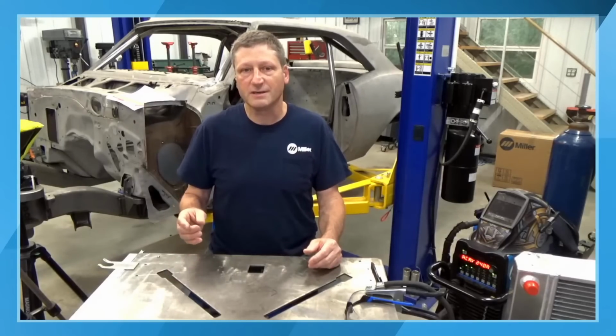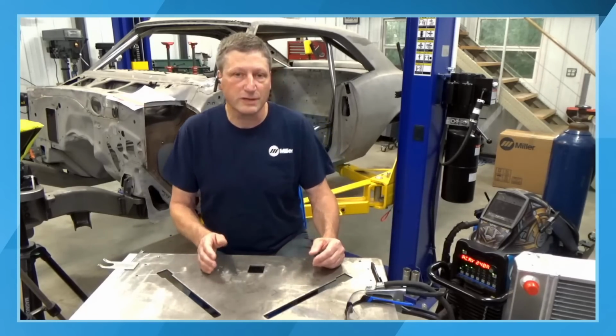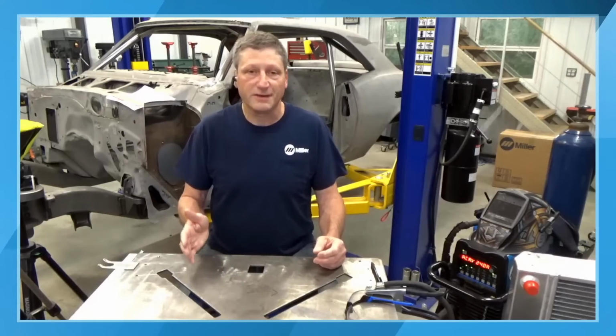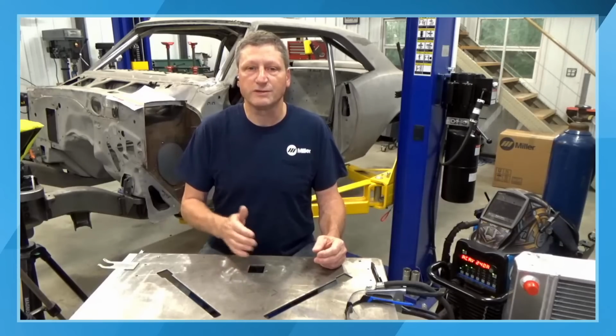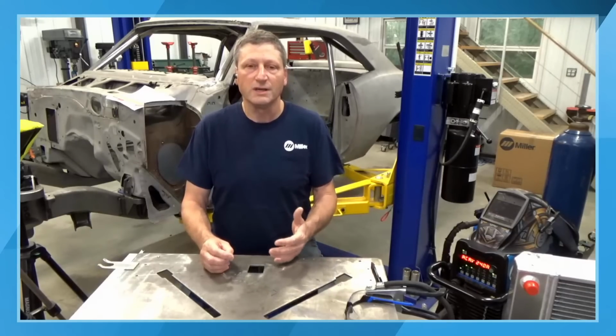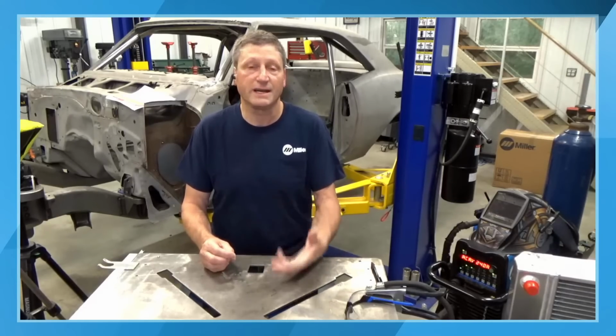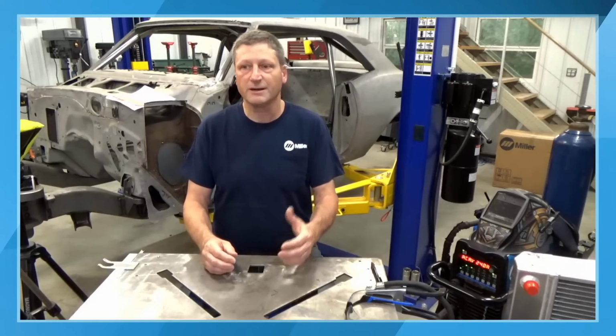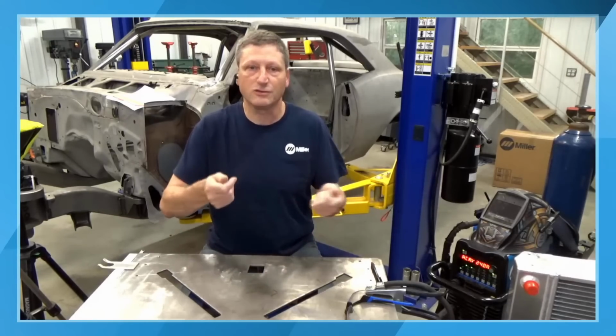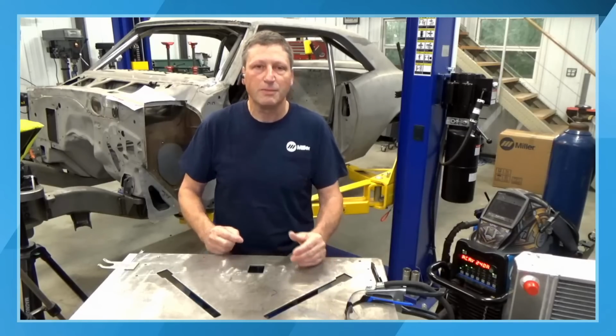Now, when you get into the alloys that aren't heat treatable, like anything in the 5000 series, the 3000 series, the only way you're going to return that to a higher temper is probably cold working it. Anytime you're hammer forming it, you're adding more temper to it. If you're rolling it in your English wheel, you're cold working it. You might get it back close to an H14. I don't think you'll get it all the way up to an H34, but you probably get it up to an H14 just by cold working it.